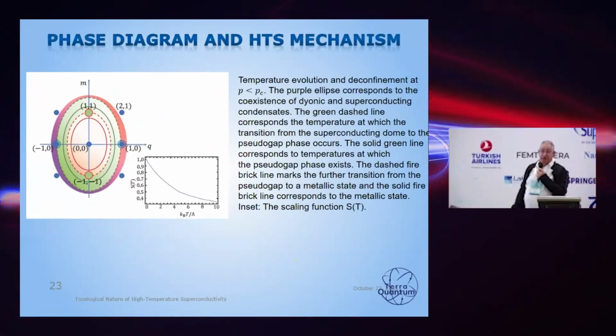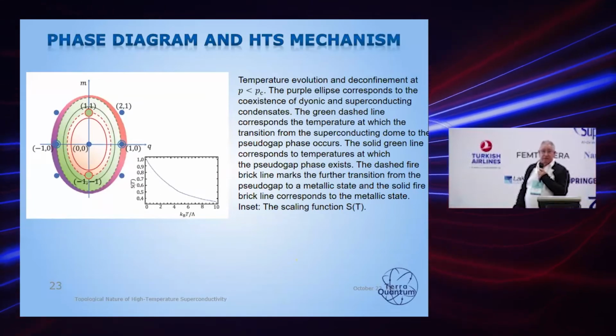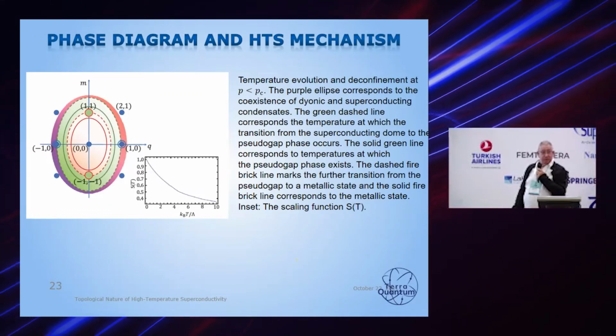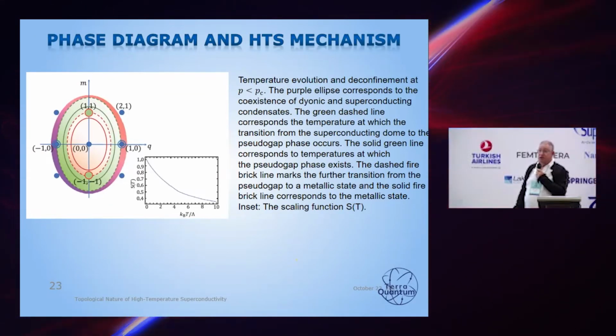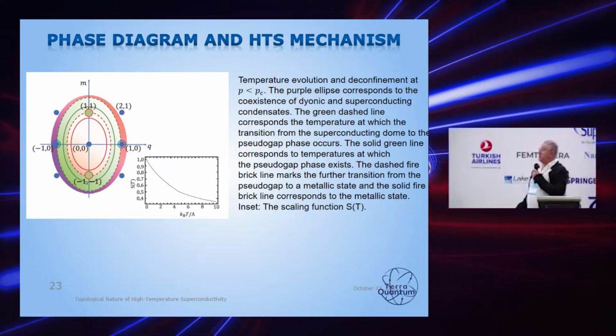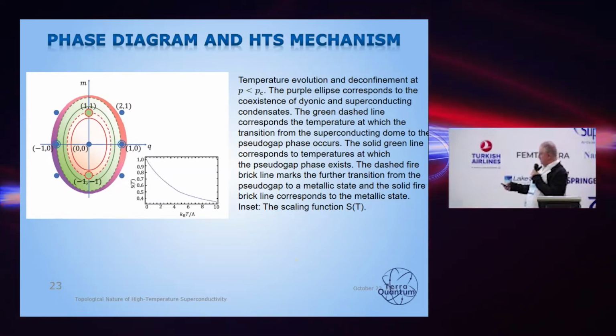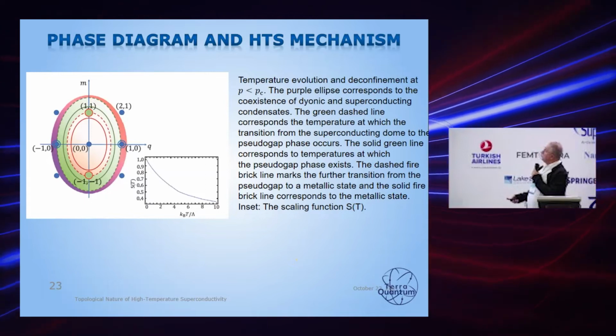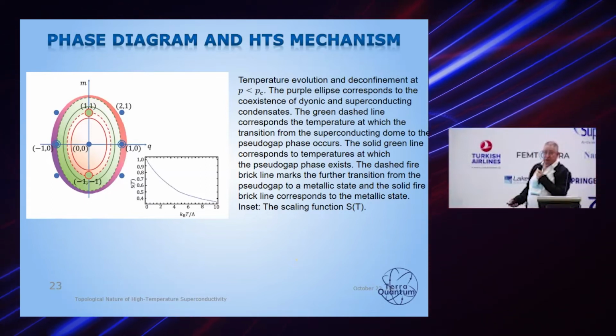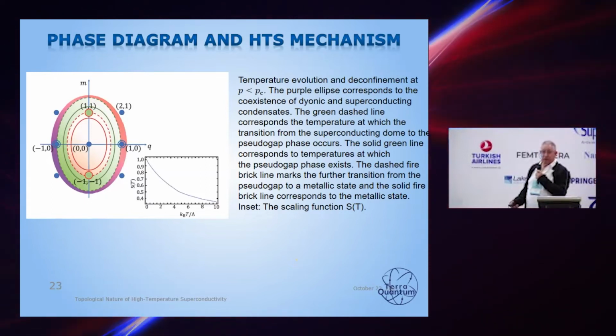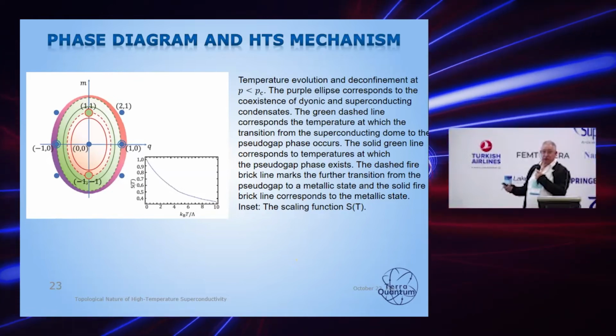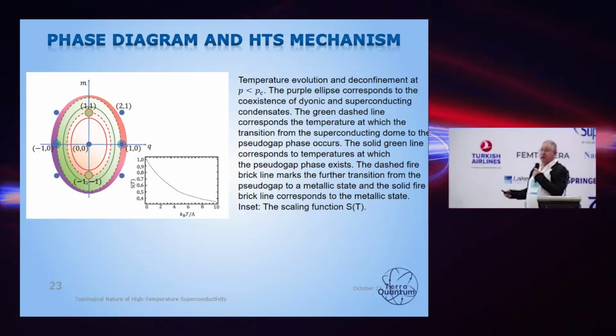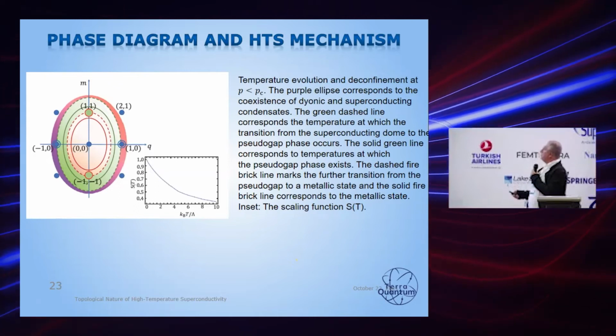If we have finite temperature, then the ellipse size shrinks together with temperature, and then we immediately obtain all the transitions from the pseudogap state to a normal metal, or the transition from a superconductor, if we are in an overdoped region, again into the metallic state.